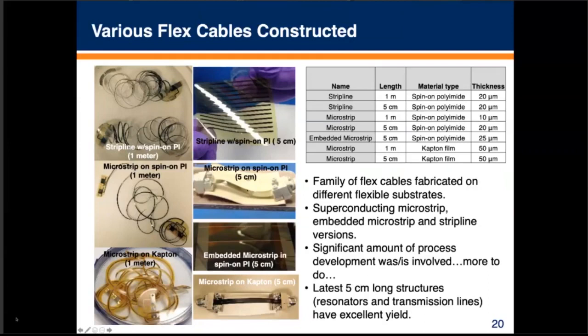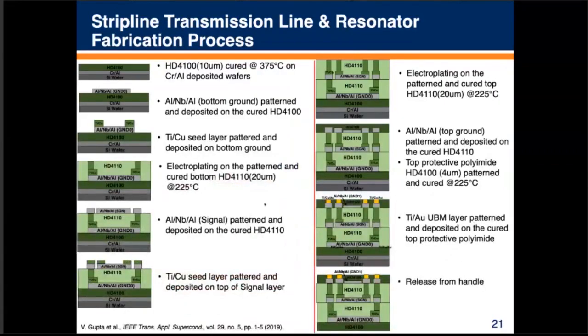But a lot of the structures that we test are just meandered traces on this. So we can still get the length, but deal with the smaller, more manageable test structure. In terms of the fabrication process, it's quite similar to dealing with the microstrip that I mentioned earlier. And in this case, I'm still showing the chrome aluminum release process. We can build the whole thing on a fused silica wafer and then use an excimer laser to release this as well without having to use the chrome aluminum.